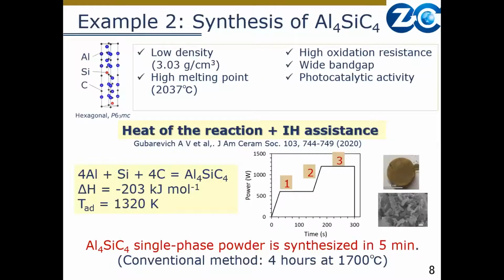Next, let me explain about synthesis of aluminum silicon carbide. This is a novel material. Its crystal structure is shown here. It has low density, high melting point, high oxidation resistance, wide band gap, and photocatalytic activity. Despite this material being very interesting, research on aluminum silicon carbide is still restricted by the difficulty of synthesizing a single phase. Here we proposed our method to use heat of the reaction and induction heating assistance.